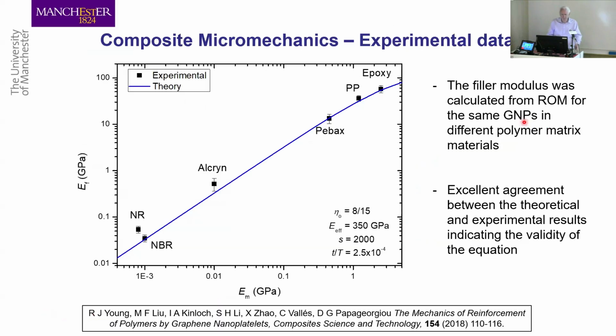So if you look at our data now, cleaned up here, this is where we do the log-log plot again of the modulus of the graphene against the modulus of the matrix, going from natural rubber, soft materials, to more rigid materials, thermoplastic elastomers, epoxy resins. You find the graphene starts to get reasonable properties as you get stiffer and stiffer. And this particular line is asymptotic to 1,000 gigapascals. So because of the mechanics, because of stress transfer, you only get very high modulus values for the graphene in high modulus matrices. That's a little disappointing, but in fact, it explains quite a lot.